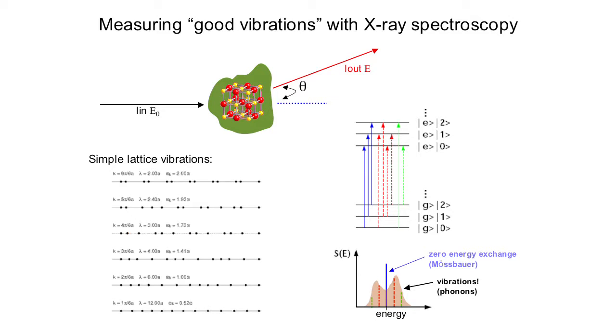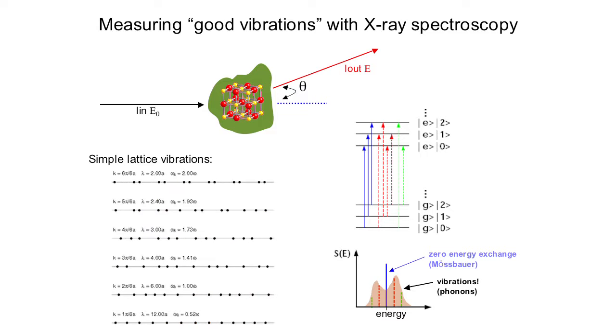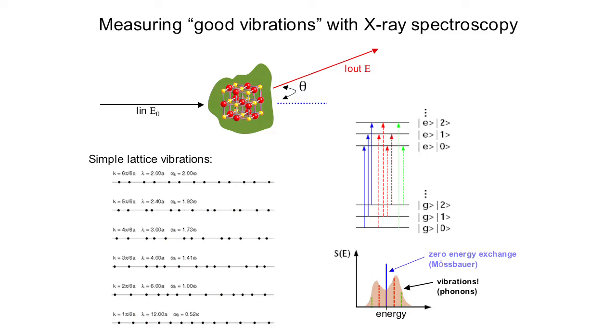So how do we do these measurements? We introduce X-rays with a very specific energy that interacts with the lattice that is vibrating. So it interacts with these motions. And after that interaction, it is changed in energy. And that energy change is proportional to a specific vibration.